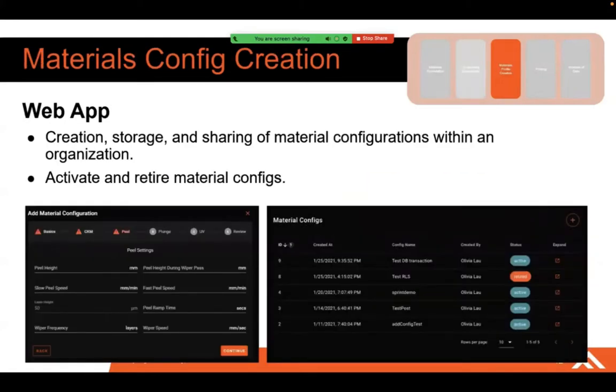There are more tools to Flux Developer. We also have the web app, which is a browser-based interface where our users can create, store, and share material configurations within an organization, and also activate and retire specific material configurations, letting our customers choose which configurations are active and available on the printer, or retired because they've been replaced by something more relevant or a configuration that's been updated. It's in this material configuration creation tool that our customers can adjust peel settings like peel speed and layer thickness, and other things like UV intensity and UV dosage for every layer.